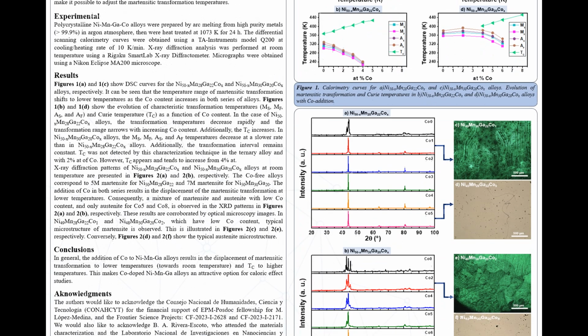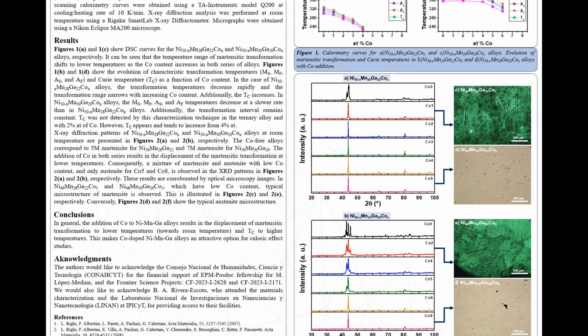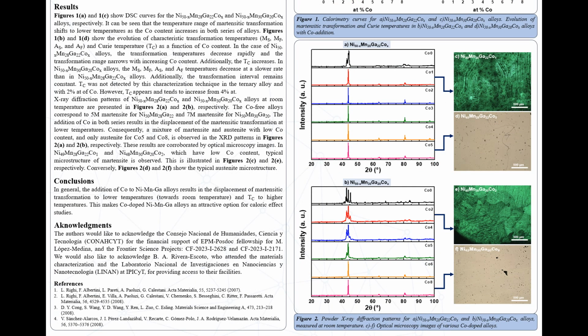X-ray diffraction patterns of Ni50-xMn28Ga22Cox and Ni50-xMn30Ga20Cox alloys at room temperature are presented in Figures 2A and 2B, respectively. The cobalt-free alloys correspond to 5M and 7M, respectively. The addition of cobalt in both series results in the displacement of the martensitic transformation to lower temperatures. Consequently, a mixture of martensite and austenite is observed for low cobalt content, and only austenite for the highest cobalt contents, as can be seen here and here.